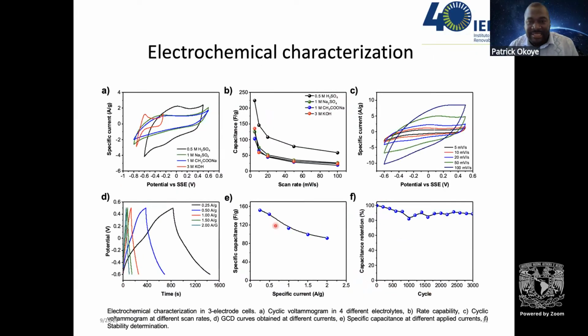Electrochemical characterization of this material shows that we have an excellent capacitance, and we tested it in different electrolytes. And we found that the best electrolyte for this was acid electrolyte. Of course, people will ask, why not use neutral electrolyte compared to acid electrolyte? And I'm going to tell you the reason a little bit now.